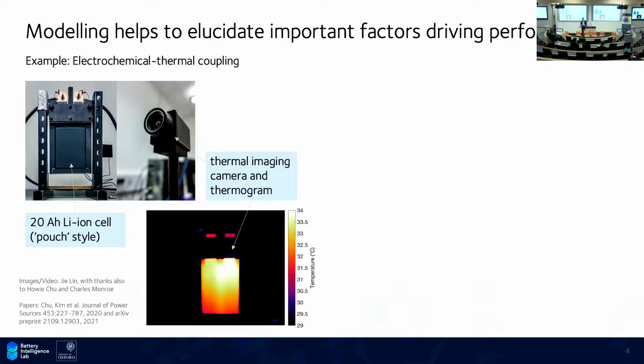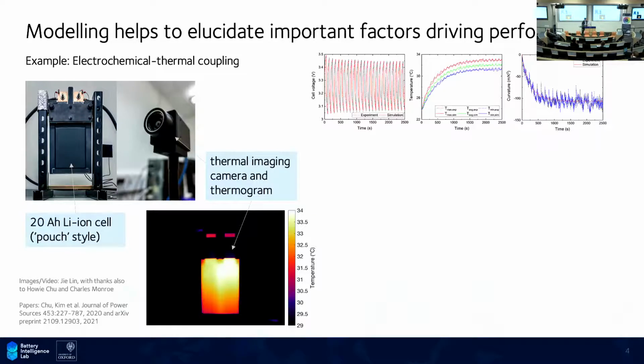And here's an example from some work being done by one of our former postdocs called Jie Lin, in collaboration with my colleague Charles Monroe in engineering. If you take a thermal imaging camera and point it at a large pouch cell, so this is a lithium-ion battery about the size of an iPad, which we've painted with paint so it looks better from a thermal point of view, then if you cycle it, you tend to get a hot spot forming like this. And if you cycle it repeatedly, you start to see an envelope of temperature as the whole thing warms up and some little wiggles forming as well, which is quite interesting.